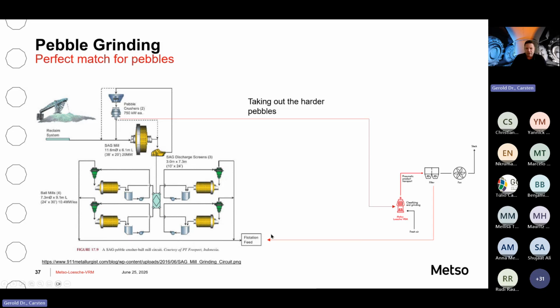So you basically have a primary feed for your flotation process, and then you can decide if your pebbles are different in mineralogy. You might even choose a different flotation circuit. Other than that, you can just combine it with a product of the wet process. And wet processes always have the issue that they are not constant in feed. So that will even be an ideal solution, because if you have fluctuations in your wet circuit, you can easily stabilize the feed to flotation with that dry product, because you can dose it exactly the way you need it.